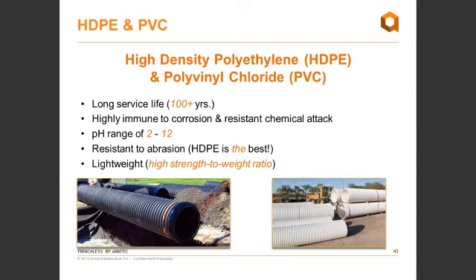So I'm going to talk about high-density polyethylene and polyvinyl chloride, or HDPE and PVC. And really, moving from coated steel to plastic, the biggest benefit is extending the service life of your pipe. Plastic pipe is basically immune to corrosion and also very resistant to chemical attack, particularly HDPE. There are not a lot of chemicals that can actually harm that plastic. Jet fuel is one of them, so don't be pumping jet fuel through your HDPE pipes, but for the most part, these pipes are supplied in some very nasty conditions in mining and oil and gas industry. So the pH range of the water flowing through these pipes is a very wide range, anywhere from 2 to 12. So from acidic to very alkaline conditions is not a problem for plastic pipes. Obviously, definitely a problem for a galvanized pipe.